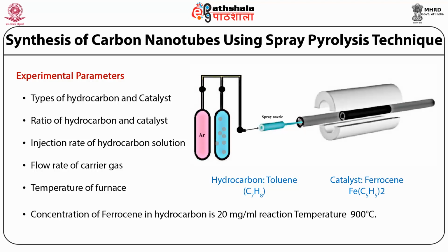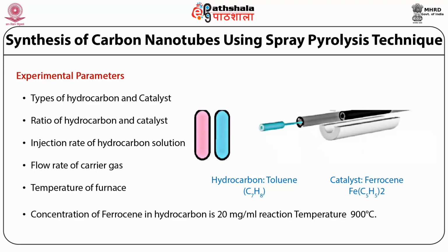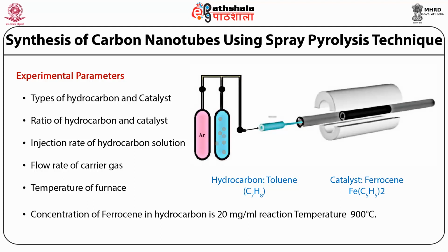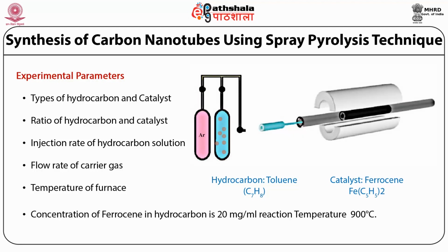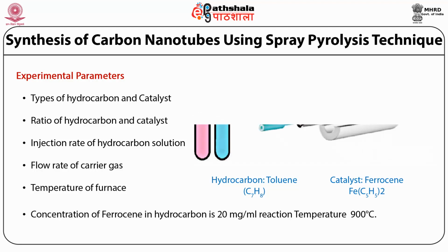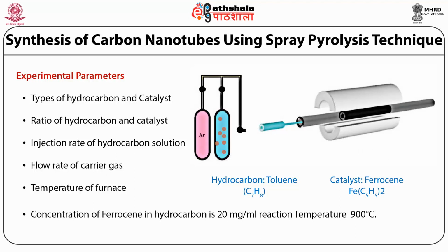Toluene ferrocene solution was injected into the quartz tube using argon as a carrier gas. The temperature of the furnace was raised up to 900 degrees Celsius. The formation of CNT microstructure was strongly dependent on the nozzle size and flow rate of solution. The removal of the assembled bulk nanotube column was done carefully by infiltration of acid along the inner wall of the quartz tube.